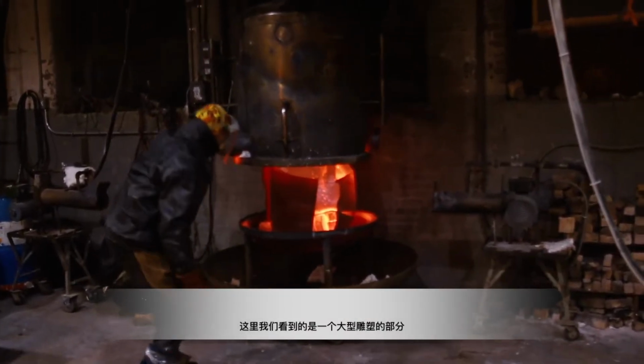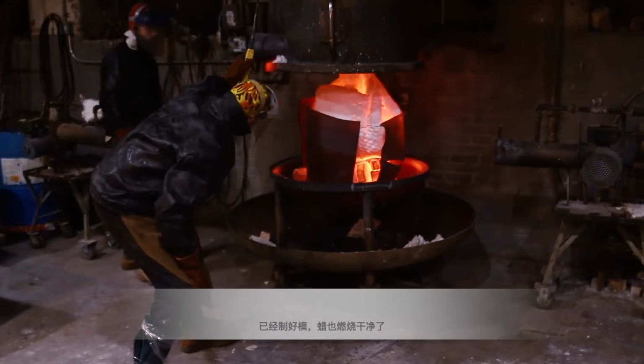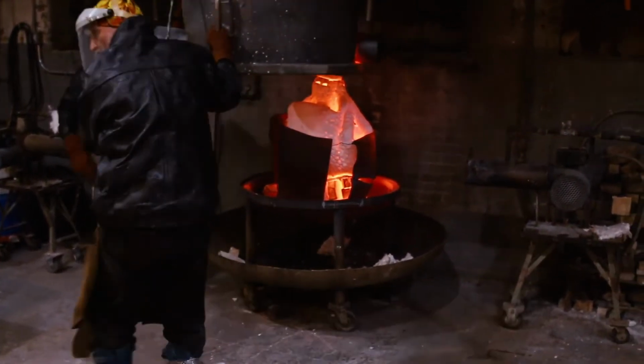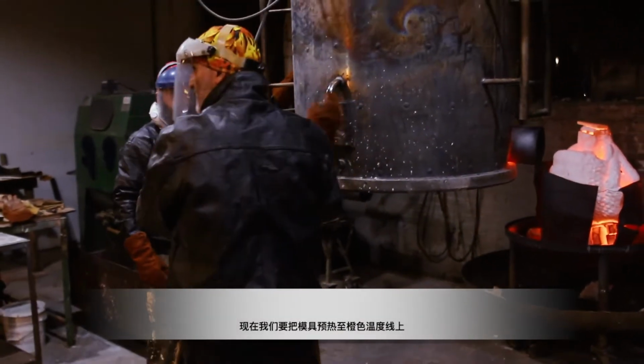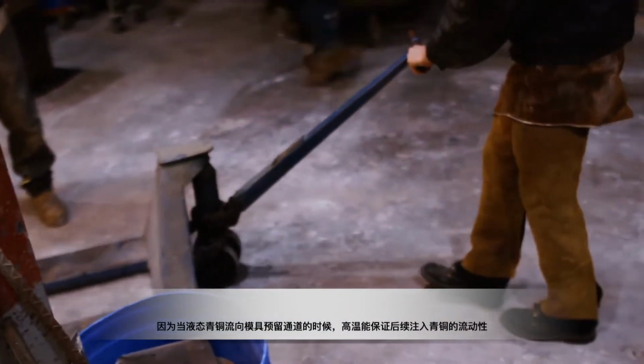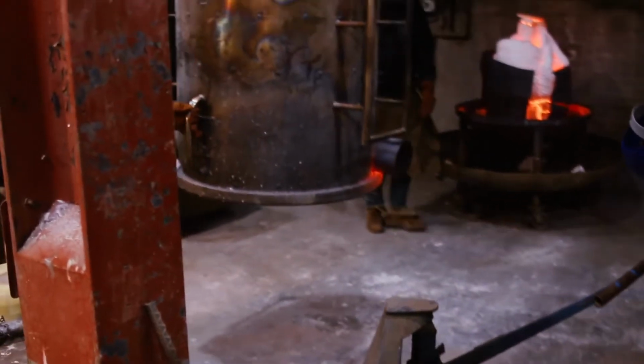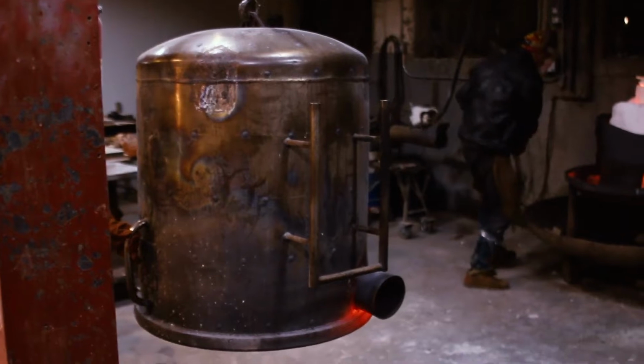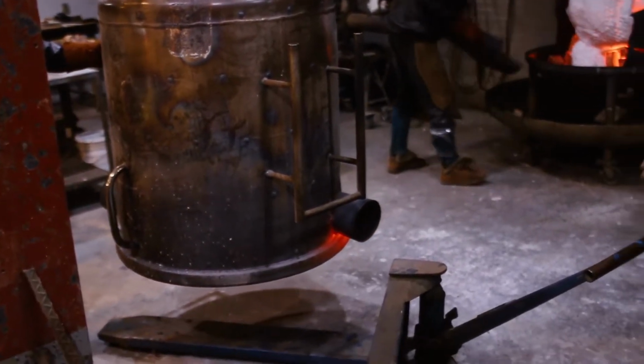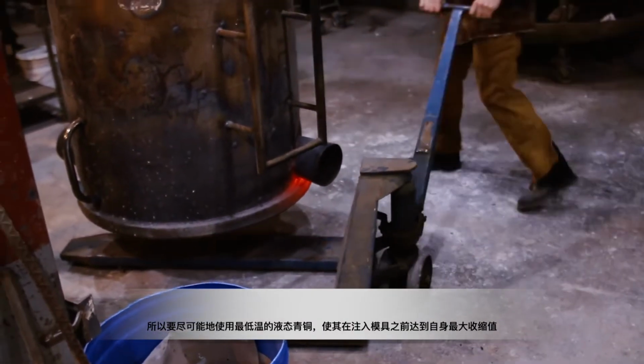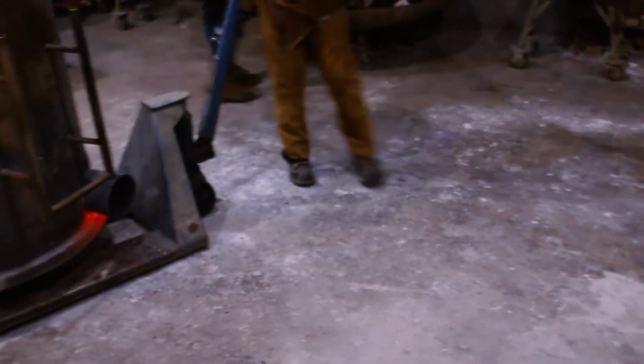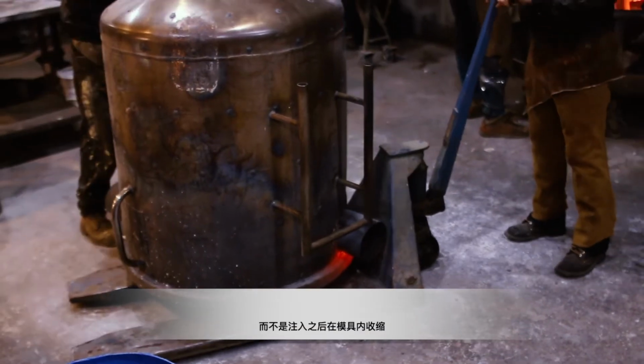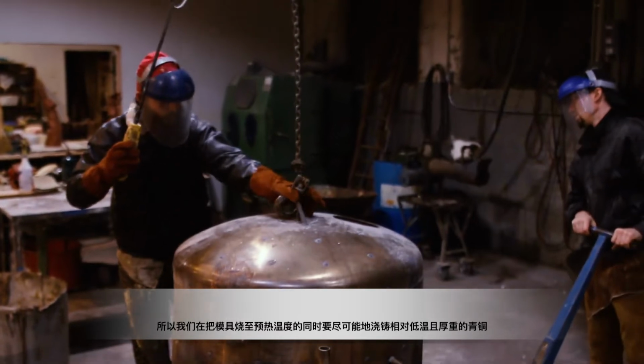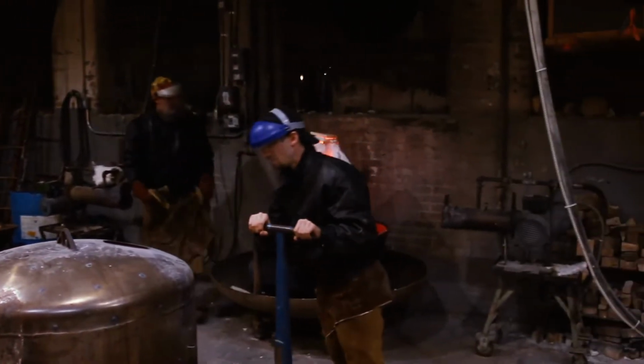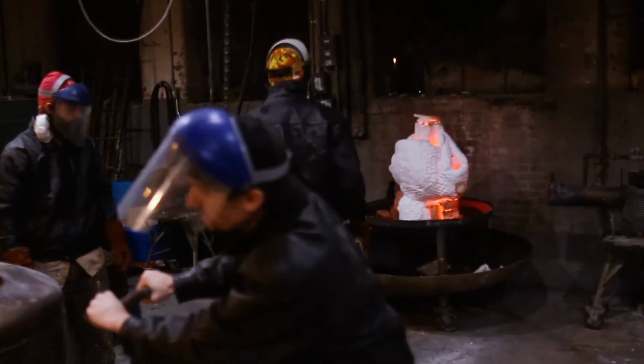Here we have a large section of the sculpture that has been molded, and the wax has been burned out, and now we've preheated the mold till it's orange hot. And the reason for having a hot mold is so that it offers the least amount of chill resistance to the bronze as the bronze floods the chamber. So I try to bring the bronze to the lowest temperature possible so that it shrinks the most in the crucible itself, and not shrinking in the mold. So by having the mold hot, then I can pour the metal as cold as possible, cool it as thick as possible, and still have it runny.